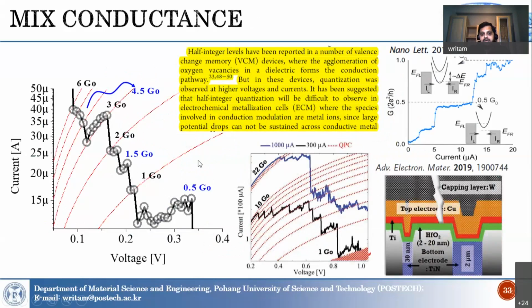So you do not have only jumps like 6G0, 3G0, 2G0, or only the even or odd integer jumps. Rather, you have some half-integer jumps like 1.5 G0, 0.5 G0, 4.5 G0. Those are really obvious.